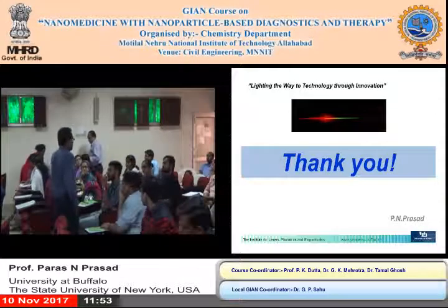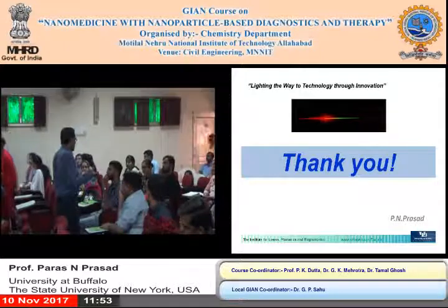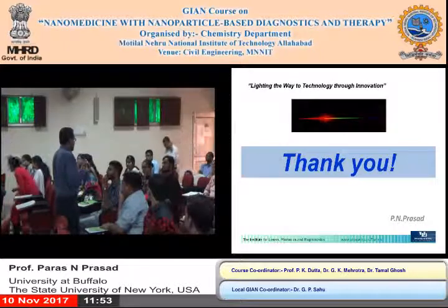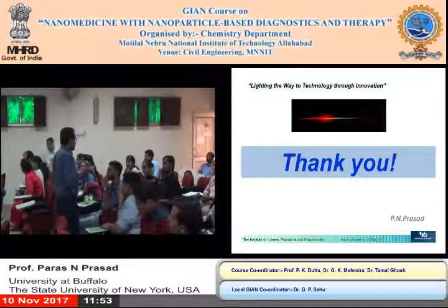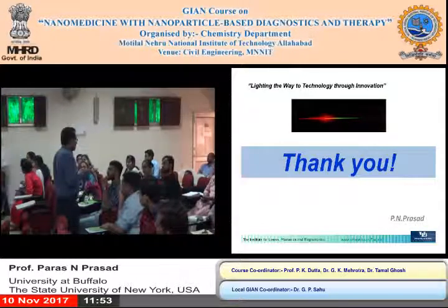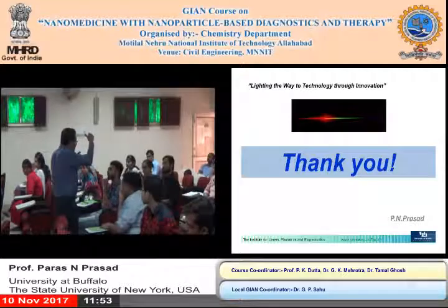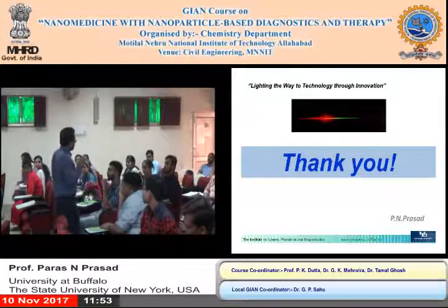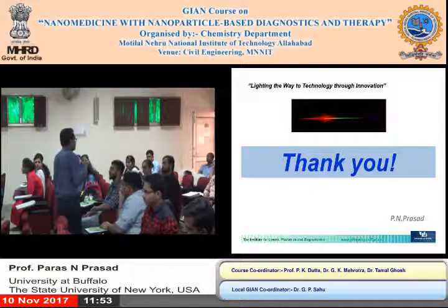So you need to see what you want to accomplish. It's not one element being better than another. You need to look at what property of that element you want to use. You cannot use erbium for generating light in the blue and UV. You need to use thulium ion because erbium doesn't have those energy levels. So you need to select on the basis of the properties of these elements or atoms.